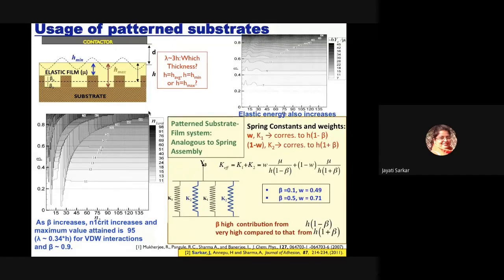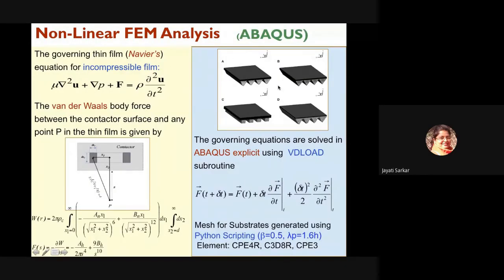films. So to actually understand this, we needed to do a nonlinear analysis, and we wanted to do it over different substrates. The way that we did it previously was not possible, because the energetics would require solving for the coefficients, and the boundary conditions were very non-linear, so we could not get the energetics out of this. So for that, we have used a finite element analysis. This has been done in a commercial software, Abaqus, and we are solving a similar expression to the one we did in the case of the liquid films.